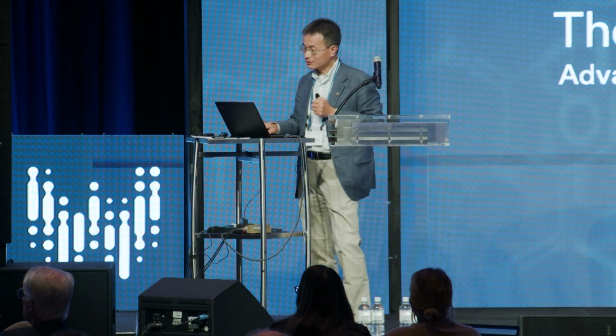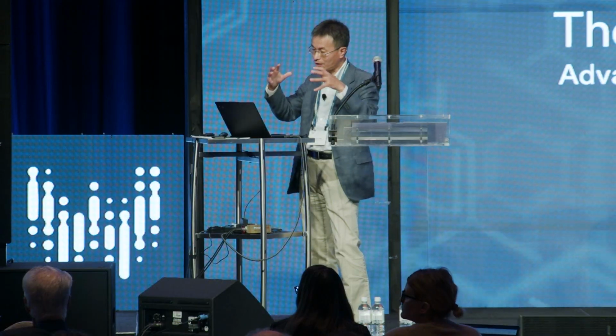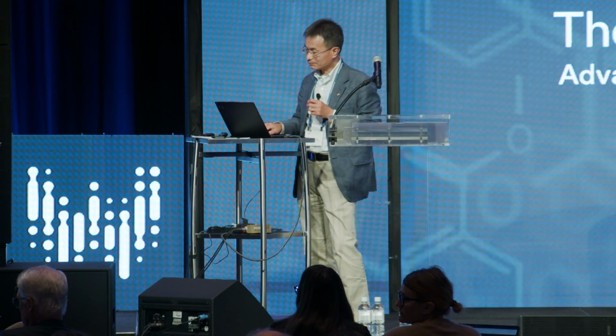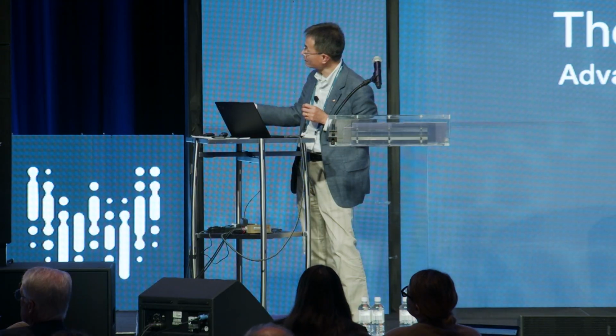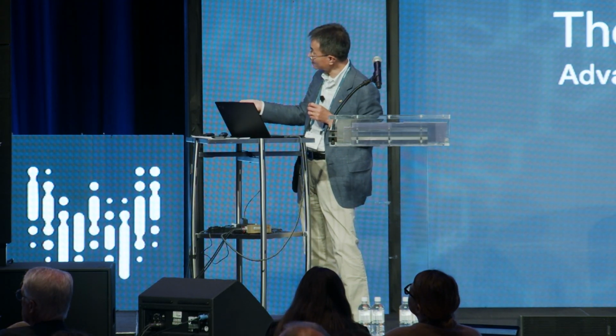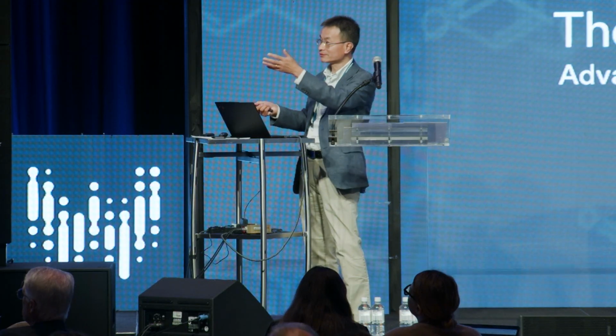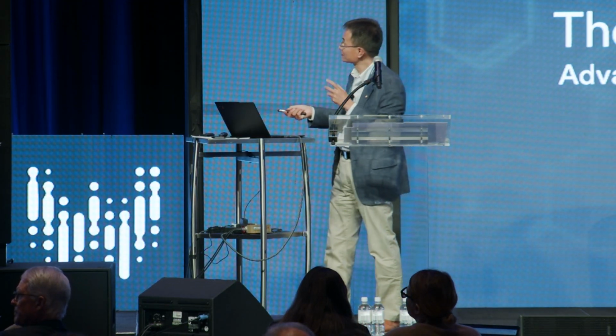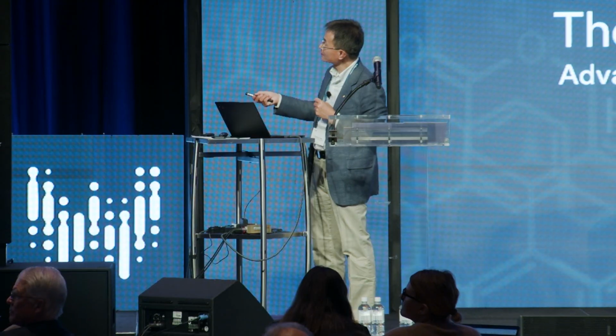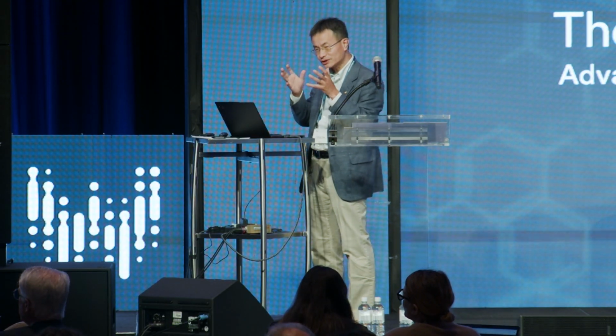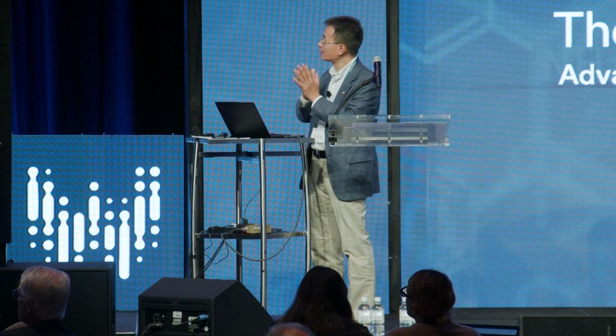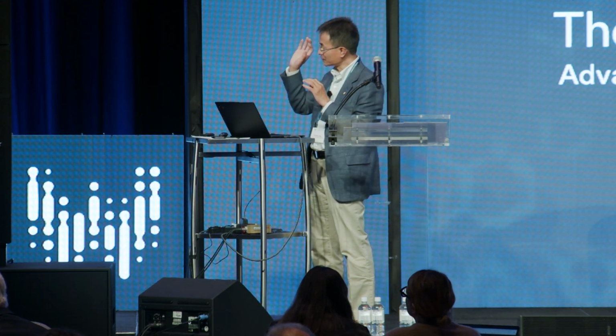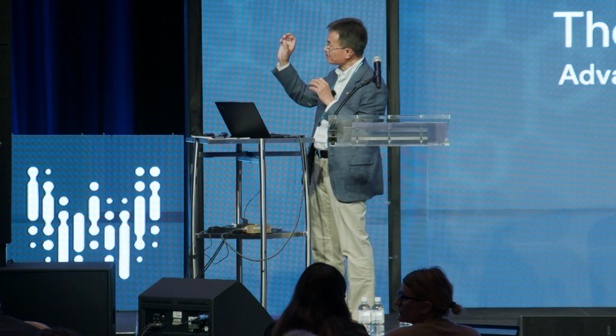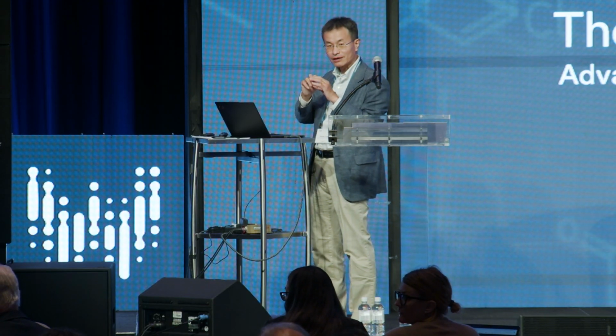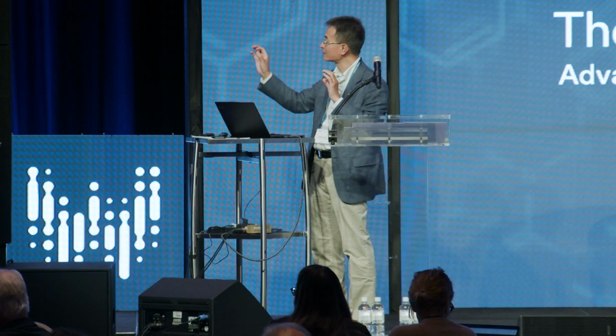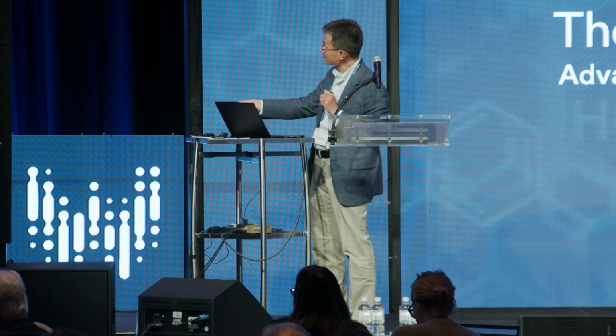So we actually revised this original bulk design of the photochemical diode by incorporating a high surface area nanowire array in the Helios program. That's back when Steve was the lab director in 2003 or 2004. You can see that in terms of the electronic structure or band alignment, this is similar to Arthur Nozik's original design. However, now it reduces down to millions of these nanoscopic photochemical diodes made out of nanowire photocathodes and nanowire photoanodes, and then they link everything together.